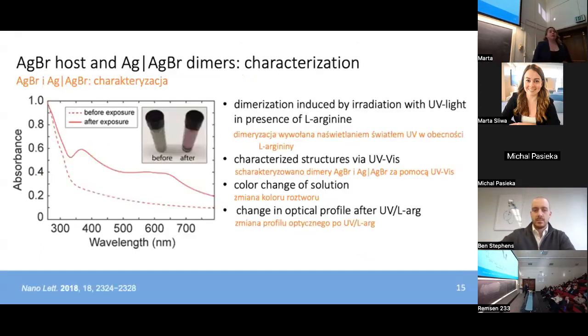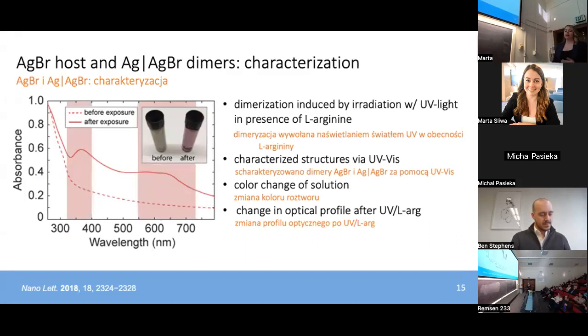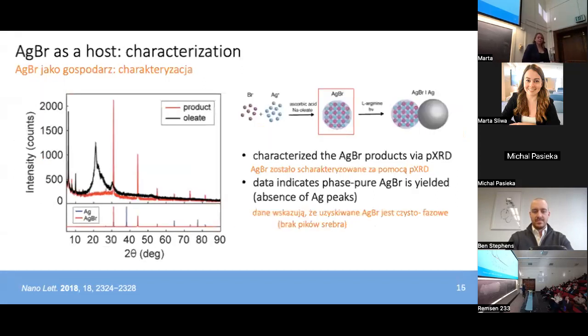So we can monitor this dimerization, or formation of that dimer, by optical characterization of the host nanoparticles before they're exposed to UV light and L-arginine, as well as the products after exposure. We see an obvious color change in the solution before and after exposure. The silver bromide host nanoparticles exhibit this gray color, and after we dimerize them, they have this purple solution color. This change in solution color corresponds to a change in the UV-vis profile of these species, with the growth of two new features in the absorbance spectrum of the dimers, here with a peak at 370 nanometers and a longer wavelength peak centered at roughly 550 to 650 nanometers once those dimers are formed. We further confirm that the dimers are only formed after that dimerization process is initiated, or the UV light and L-arginine is introduced, via powder X-ray diffraction studies of a sample of these silver bromide hosts.